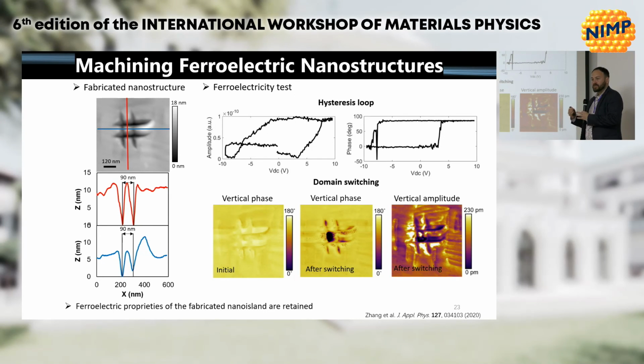Also associated with machining and removal of material, there can be a damaged layer that's reported in regular machining processes. So it could be that the quality has changed, or there's a structural phase difference there as well. Because in a normal ferroelectric, there shouldn't be a difference between orientation up and down, right? Yeah. And the shape is not completely isolated from the film, and the shape isn't square, it's following the shape of the tip or what's left over after it broke off.